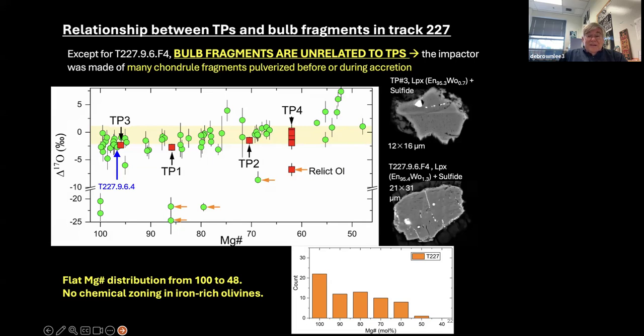One astounding aspect of the cometary olivine is the rather flat distribution of the magnesium number. So the iron content of the olivine, instead of being spiked at forsterite, pure magnesium olivine, with a tail going out at higher values, is, compared to most other meteorites, pretty flat, as shown in the histogram in the lower right hand part here.